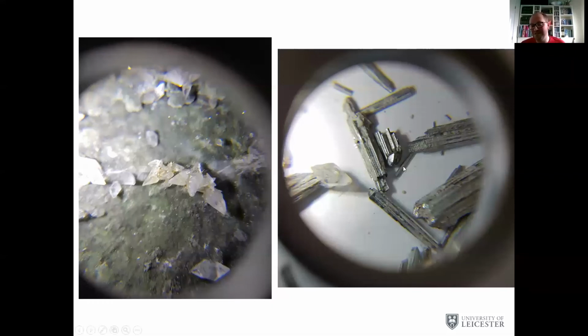This is sylvanite. So this is a silver gold telluride from Vatukoula. Beautiful crystals of the stuff, and you can get a sense of the scale of them. These are about 1 centimeter to 1.5 centimeters long, next to some calcite rhombs, next to some gold. Fabulous high-grade assemblage. Okay, but if you were to try and process that by a conventional method for extracting that gold, you would not touch this. It would not dissolve in the same fluids. And in fact, what would happen is that this would start reprecipitating native tellurium onto the surface of that gold and reduce your gold solubility. So a nightmare to process.